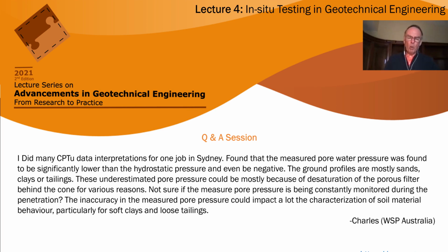So if the porous element has become unsaturated, possibly due to either a poor saturation procedure to start with, or that you were pushing through a relatively deep profile of unsaturated material, and therefore you lost the saturation of the porous element. Then when you're below the water level, if you stop and do a dissipation test, then if there are any small air bubbles in solution, air bubbles in the filter, then they will quickly go into solution and resaturate the cone. So if you're below the water table, you do a dissipation test. When it comes up to equilibrium, which is a positive pore pressure, it resaturates the cone.